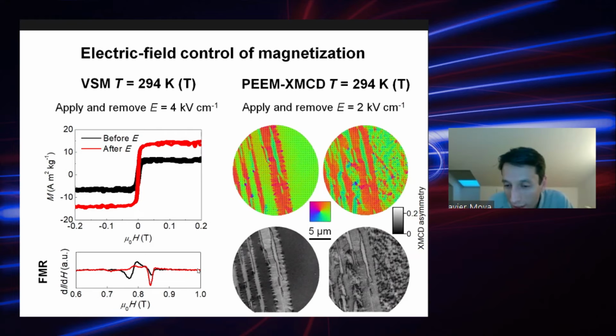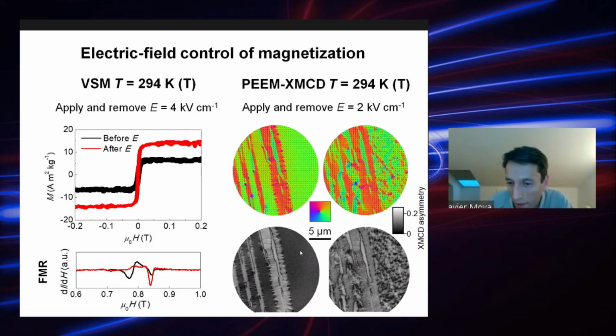So in order to understand this in detail, what we did is again magnetic microscopy at diamond. And then just if you concentrate on these two bottom images, which are easier to interpret, again, this is a map of the magnitude of the local magnetization. So here, regions that are black means that the magnetization is very small or zero. And the regions that are white are regions where the magnetization is very high. So basically, what you can see is before applying an electric field, so this image, the sample actually is made of two different regions. So regions where the magnetization is very, very small and regions where the magnetization is high, which is consistent with these two resonant peaks.